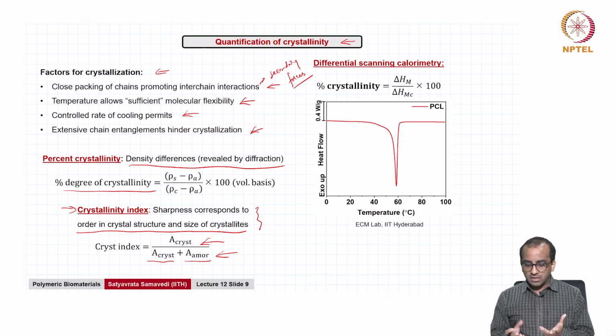Essentially, it relies upon having two different pans, if you will, in one pan you have the sample, the other is the reference pan. Broadly what you are asking is how much heat should be supplied or removed from these pans to ensure that both pans are maintained at the same temperature.